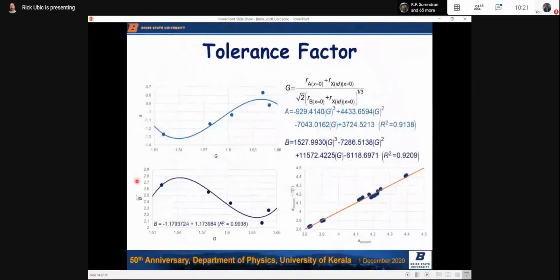Here are the A and B coefficients graphed against this weird, I don't know, my student invented this weird geometrical term. It's just a constant though. And you stuff it into these equations and you get A and B. Again, these are essentially mirror images of each other, so they're not independent. So you can describe B in terms of A, like this equation down here. And bottom line is you can then describe the lattice constant as a function of this t prime value. And you get a nice curve fit, right? Calculated versus experimental lattice constants. So I know I have to rush through that a little bit.